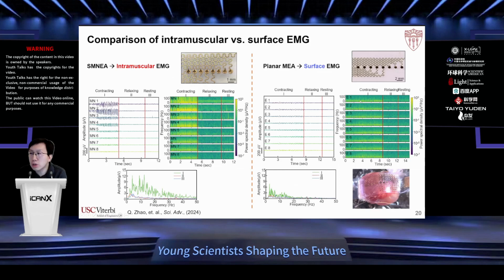If we use planar microelectrodes, we will only be able to measure surface EMG. You can see from here, the surface EMG signals across different channels are all pretty much the same, which we think is because the EMG signals, when they propagate to the surface of the tissue, have already degraded and affect each other. So with this surface EMG, we will not be able to resolve muscle-specific activities. So this example shows that stretchable microneedle electrodes are a very effective tool for us to study muscle-specific or tissue-specific targeted